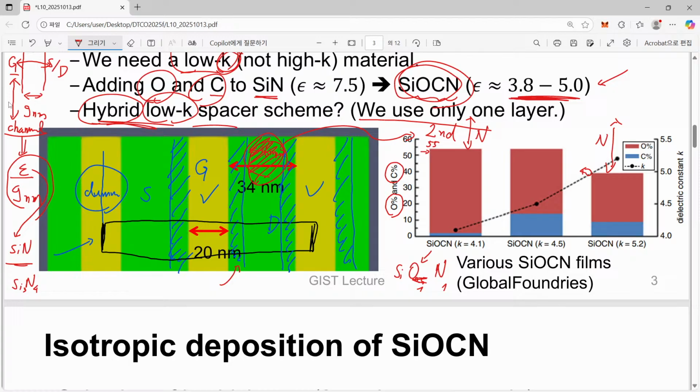This is the composition, and if we increase carbon a little bit, then kappa is increased, and if we reduce the sum of nitrogen and oxygen simultaneously and increase the nitrogen composition, then of course we are approaching a higher kappa value. It is quite acceptable. If we increase the nitrogen composition further and further, then our material will become more rigid and show a higher kappa value.